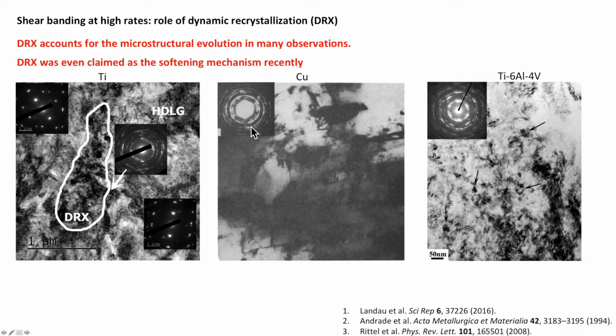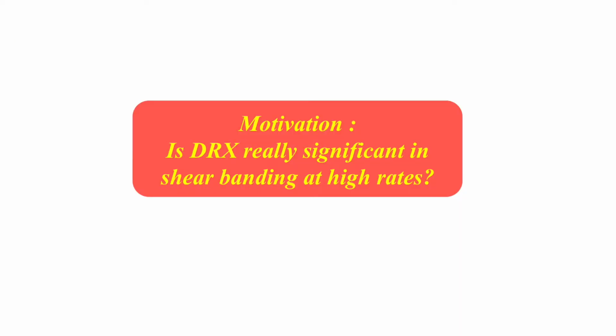Similar observations were also made in copper and Ti-64. In both cases, within the shear bands, you see rings telling us the grains have turned nanocrystalline. However, within the shear banding community, people also realized the temperature increase in some cases is not high enough to trigger recrystallization. Therefore, some arbitrary parameters have been introduced in mechanics models to explain the observed dynamic recrystallization. The question we ask ourselves is: is dynamic recrystallization really the dominant mechanism for shear band formation?